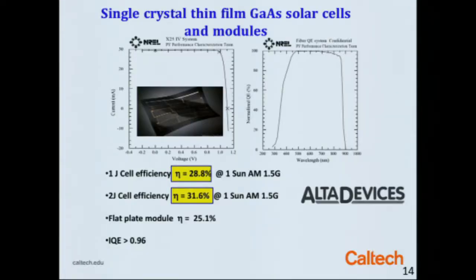This is more efficient than the world's record silicon solar cell. So you can see it there. The total semiconductor thickness is 1.4 microns thick. So the laminate thickness is dominated by the plastic that's there to keep the fingerprints off it.